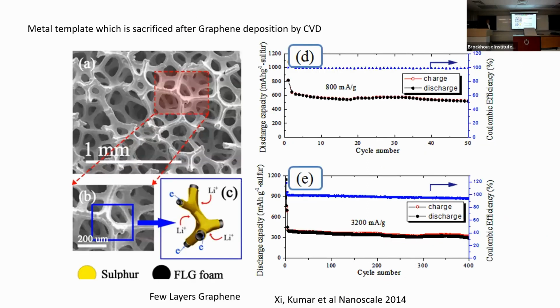And you can do the same with graphene structure. Yeah, this is again, you take a template like nickel, porous nickel, and you grow the graphenes in and then dissolve the nickel away, for example, or copper away. And then you get this structure. These are the graphene structures. And this also, you can see now, the capacity is very, very high. And remember, there's a lot of pores.